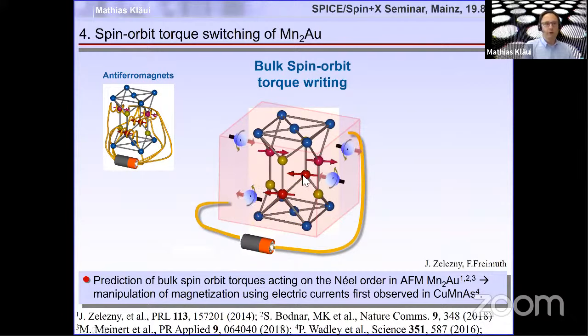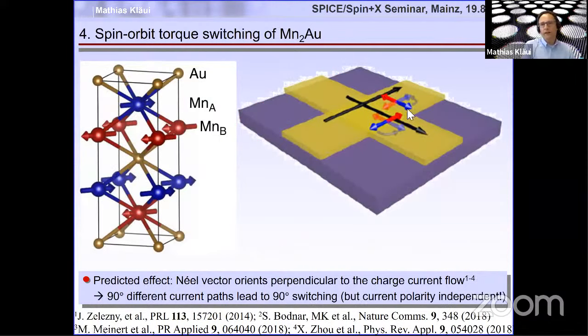And as I said, this was first observed in copper manganese arsenide in the work by Pete Wadley. And then we worked on that in manganese two gold, where we actually patterned a manganese two gold cross, whereby injecting the current, it was predicted by Jakub Zelezny and Hiro and others that you can switch the magnetic sublattices in a direction perpendicular to the injected current flow. So here, in contrast to ferromagnets, we don't get 180 degree switching, but by flowing the current in 90 degree different directions, we get 90 degree different orientations of the Néel vector.